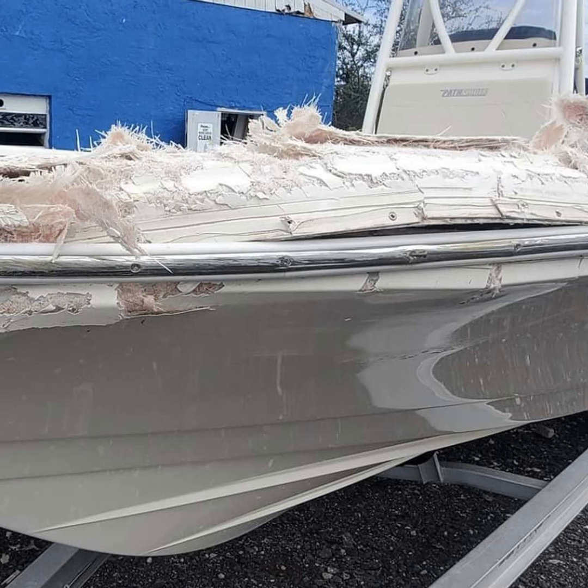So you're going to go outwards 3 inches from the furthest point where it's damaged into the good glass 3 inches. You're grinding as much fiberglass away as you can while leaving just enough to maintain the shape you need if it's a complex shape. Once you use your 12-to-1 ratio, then you can just measure and mark around it with a wax pen or a Sharpie or a pencil or something like that.